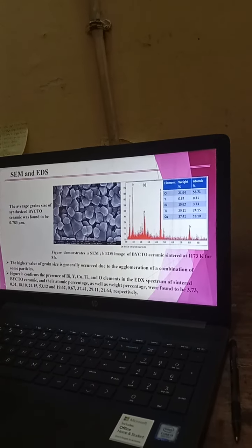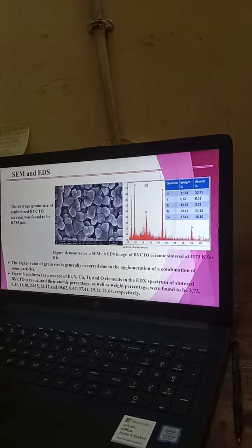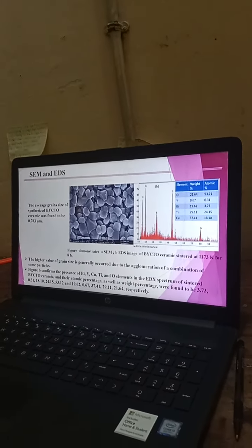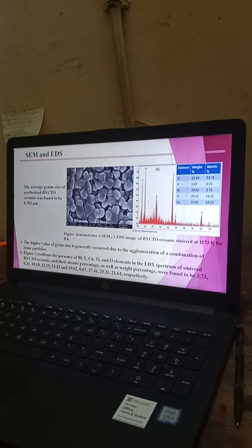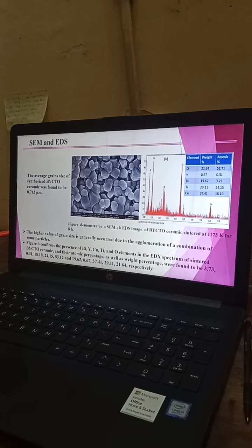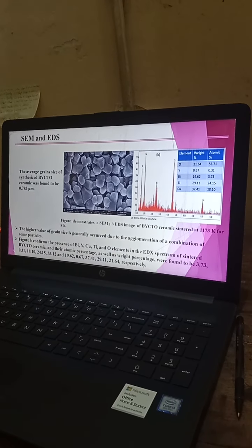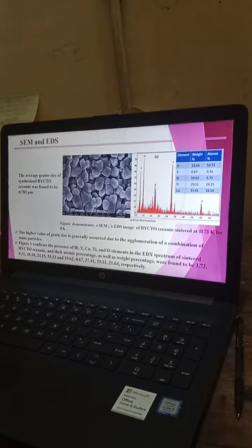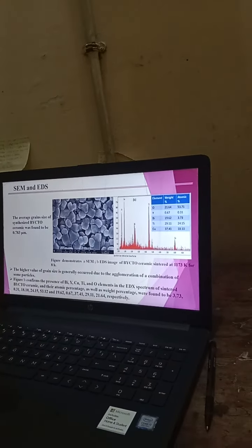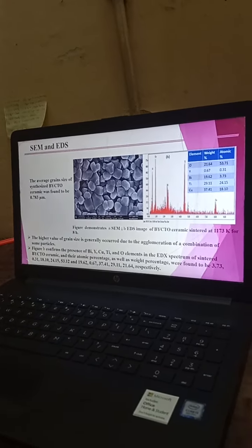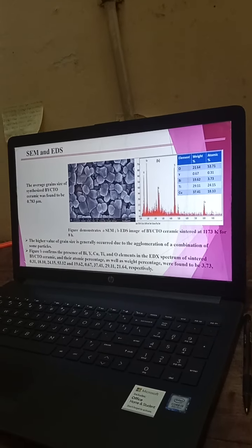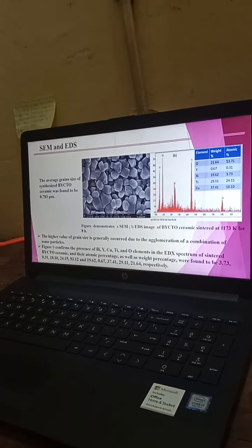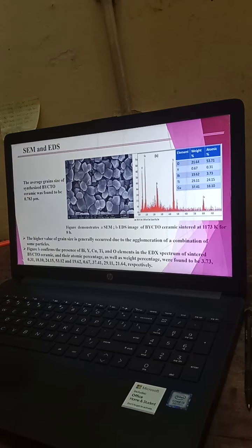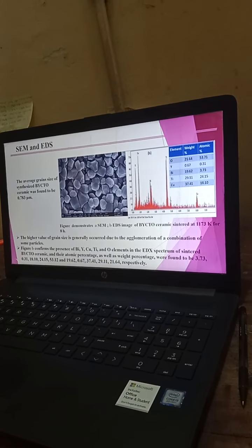The average grain size of the synthesized BYCTO ceramic was found to be 0.783 micrometer. Figure B represents the EDS image of the BYCTO ceramic sintered at 900 degrees centigrade for 8 hours. From figure B we have confirmed that the elements bismuth, oxygen, copper, yttrium, and titanium are present in the material, and the purity and the stoichiometric amount were also verified by this EDX spectra.